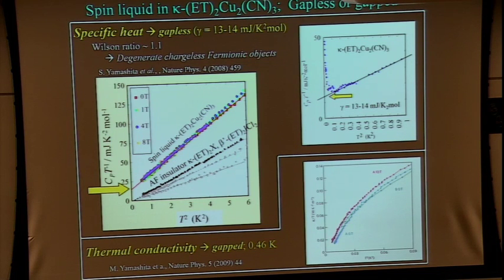So even in this respect, there is no agreement. But I have to say that specific heat is a purely thermodynamic quantity, and thermal conductivity is thermodynamic in some sense, but in another sense it's a transport quantity. Under the magnetic field, how thermal energy transport behaves depends on the samples, the degree of disorder or something like this. So thermal conductivity is very sensitive to such sample conditions. But I'm not sure. Anyway, this is some sort of transport measurement.